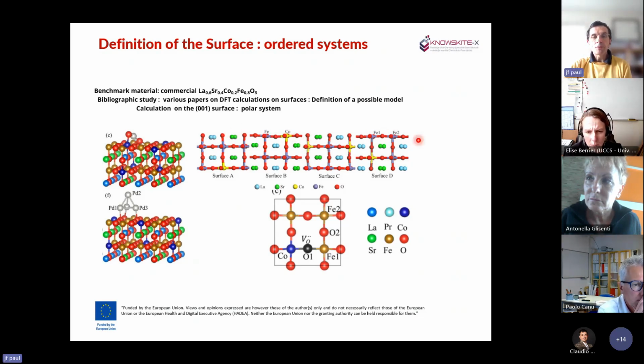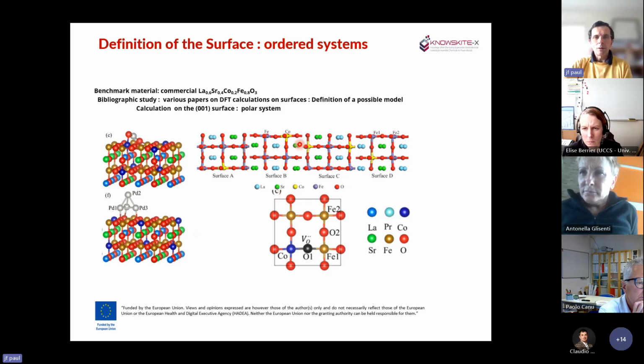And here you have the type of surface that you can create. You can see that, however, the system is really well ordered, and you create layers or lines with lanthanum and lines with strontium, and you also create a plane with cobalt and a plane without cobalt, and you also have a line of cobalt in your system. So the system is quite good, but you don't have a lot of flexibility to really see what is happening and how to consider the activation of O2.